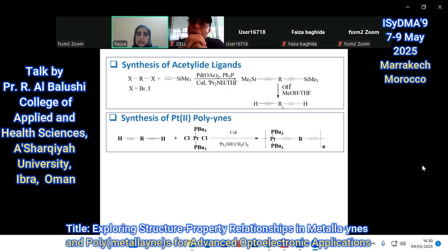Once we have the deprotected ligand, which is not very stable, we directly react this terminal ligand with the platinum salt, using copper iodide and the amine as a solvent, in order to enhance this polycondensation reaction in a 1:1 ratio between the platinum salt and the terminal ligand.